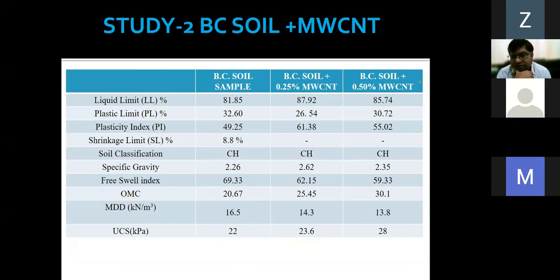because carbon nanotube is very costly, but carbon nanotube imparts great strength to concrete material because of CSH gel modification. So we attempted to see the effect of multi-wall carbon nanotube in black cotton soil and bentonite also. I have not quoted all the results because that research is still going on. But when we added 0.25% by weight and 0.5% by weight, not much difference was found. So we can say that carbon nanotube does not have that much effect.